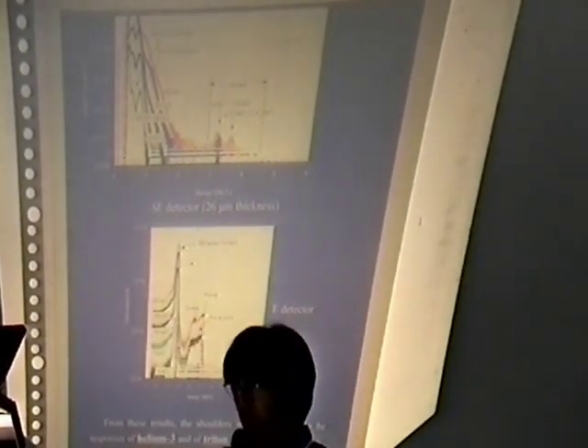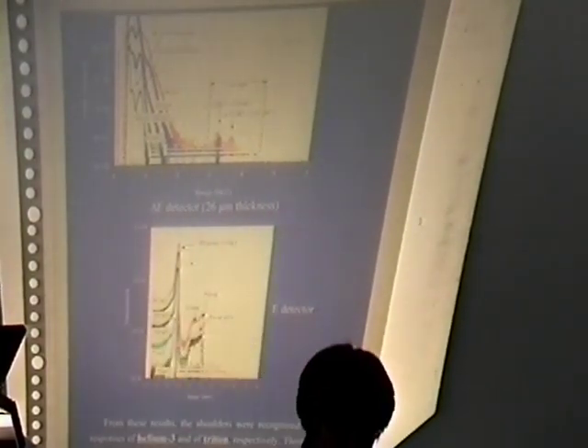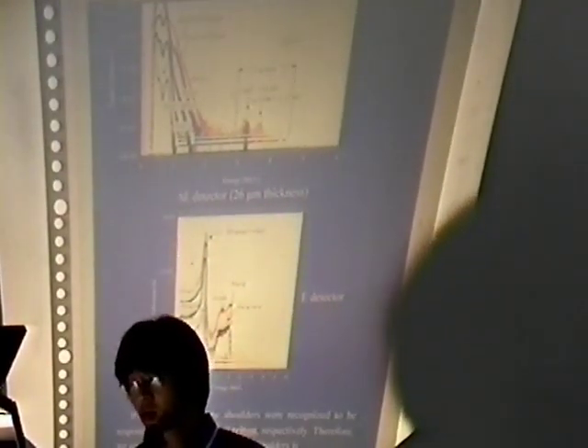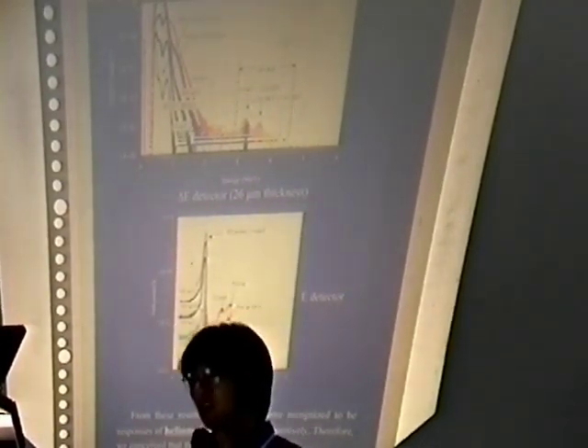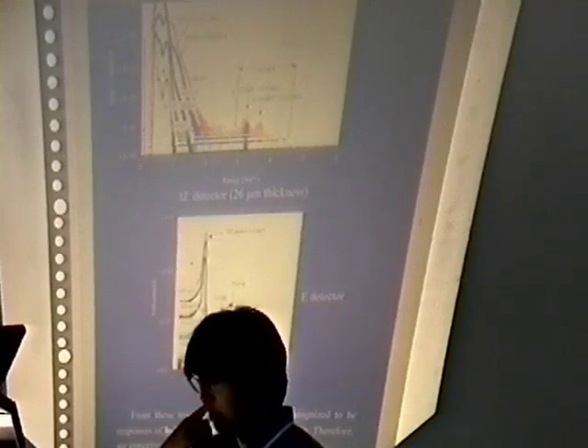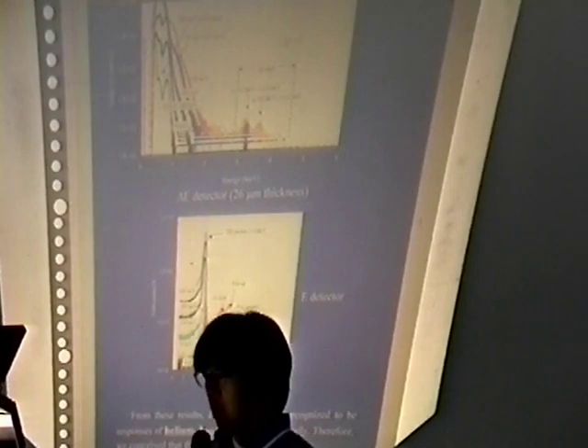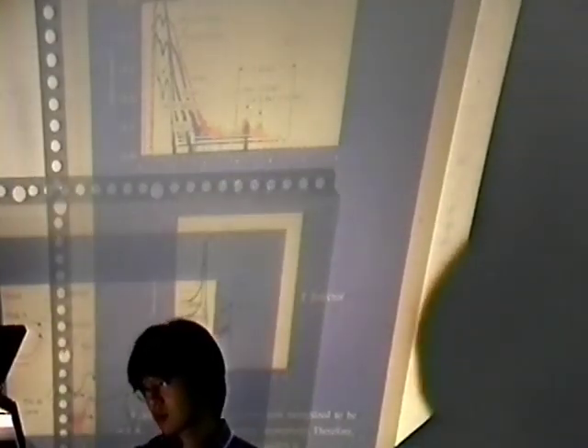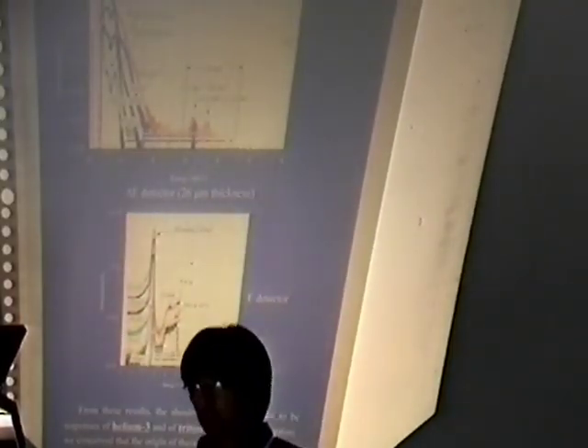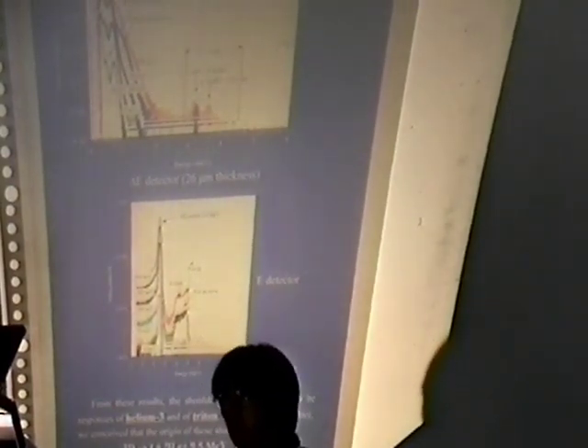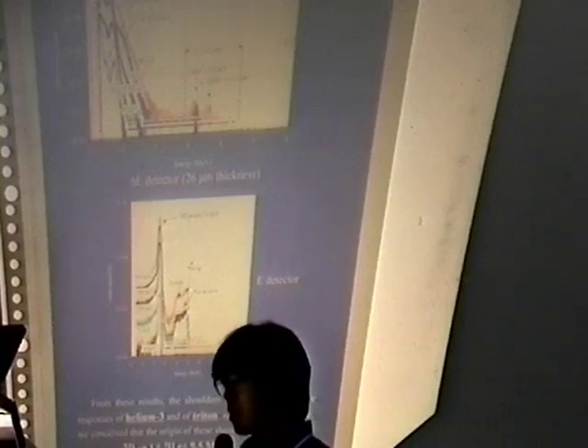The upper figure is measured with delta E detector, and the lower is E detector. And this particle, this shoulder, lost its own energy in the E detector. So we consider that this particle is helium-3, considering their stopping power in silicon. And the other shoulder is concluded to be a triton in the same way. And from these results, the shoulders were recognized to be responses of helium-3 and of triton respectively.